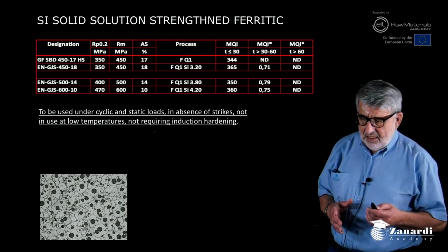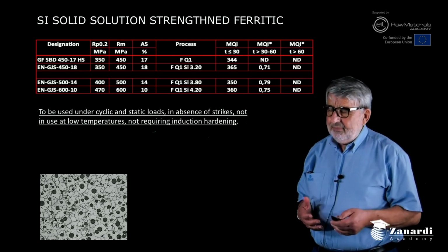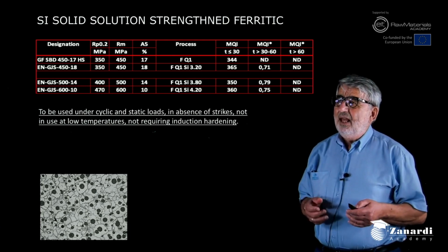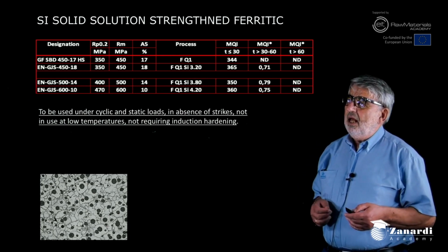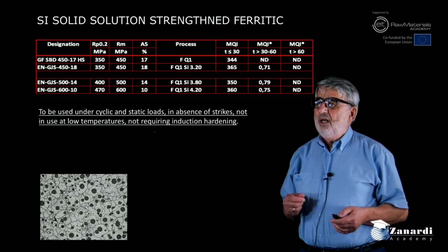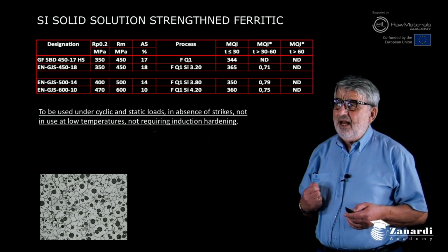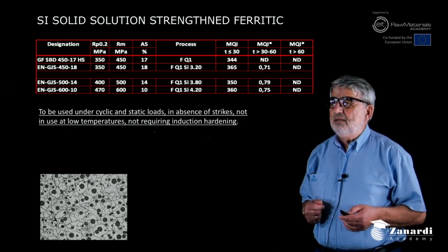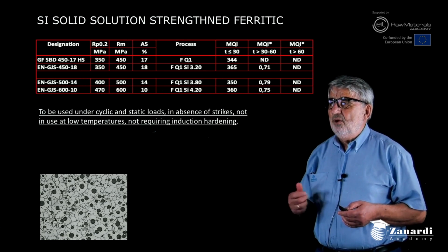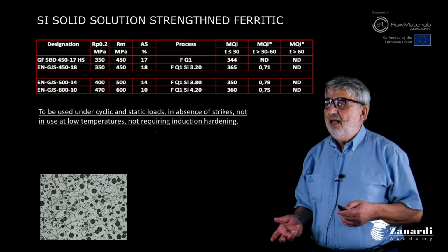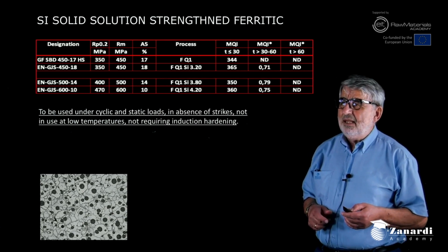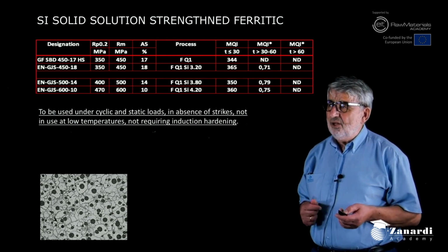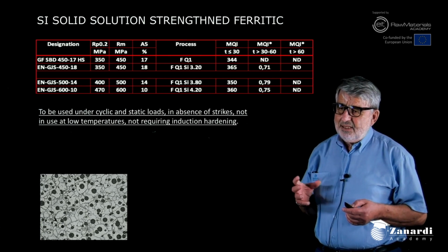But at the end, this was not enough, and grades have been developed by research programs with a very high silicon content, 4.20%, with a grade of 600 megapascal ultimate tensile strength and 10% elongation. But this grade